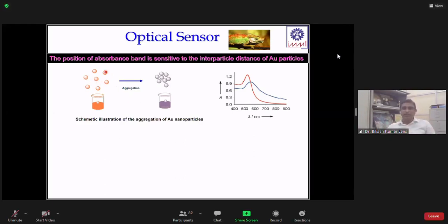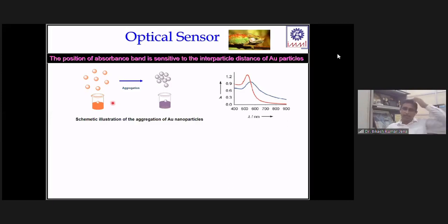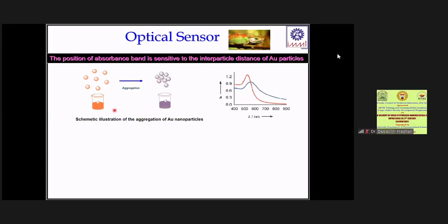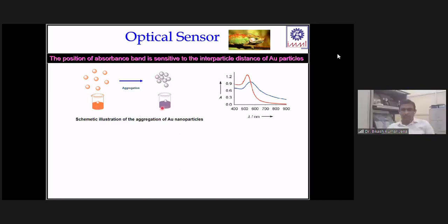You see this gold nanoparticle we developed. The absorbance depends not only on shape and size, but also on interparticle distance. If the interparticle distance changes, the color will be different. If you bring the particles closer and make a little aggregation, the color will be different. You can see this red wine color becoming purple. This is one example: we synthesized citrate stabilized nanoparticles, and when you do some controlled aggregation, the color and the absorbance property change. So we try to utilize this behavior to detect some interesting biomolecules.